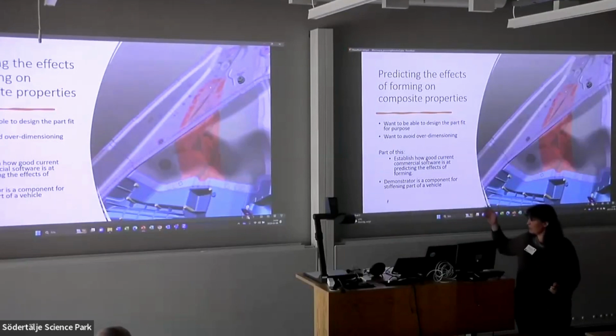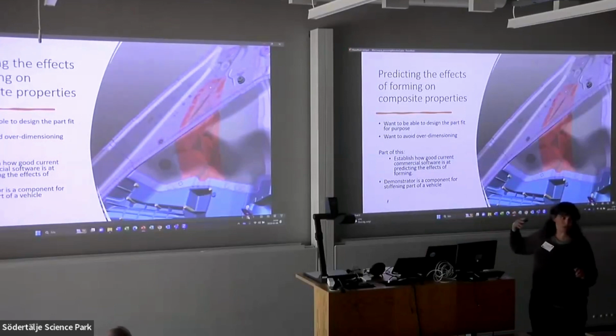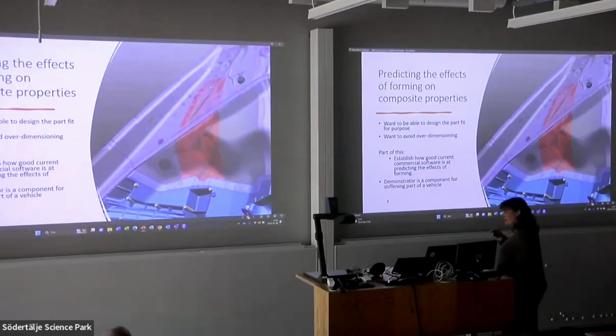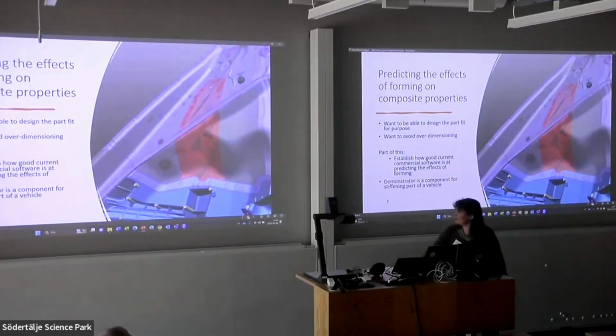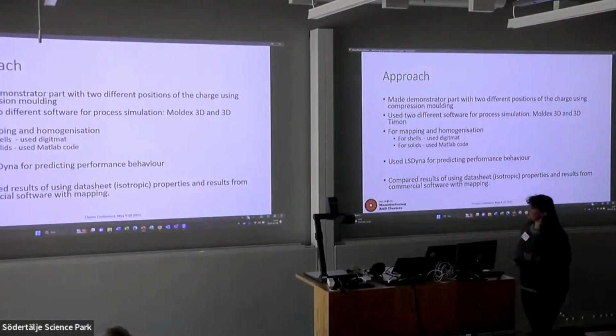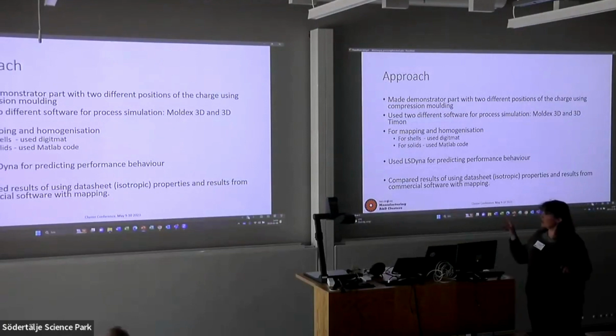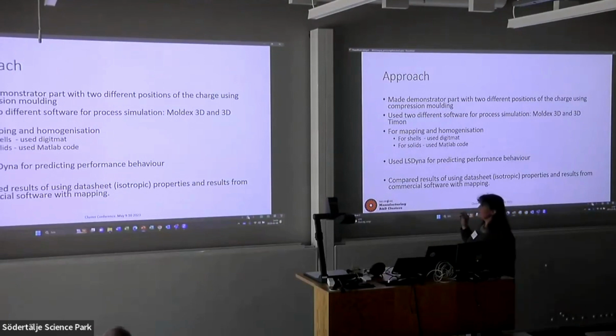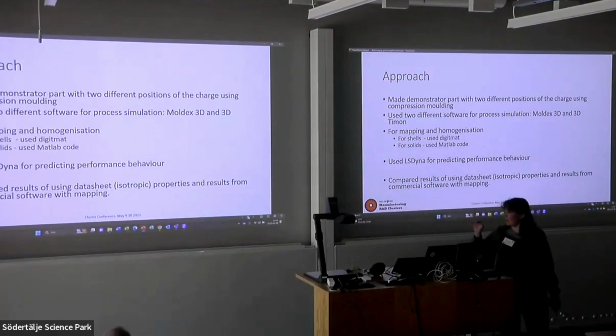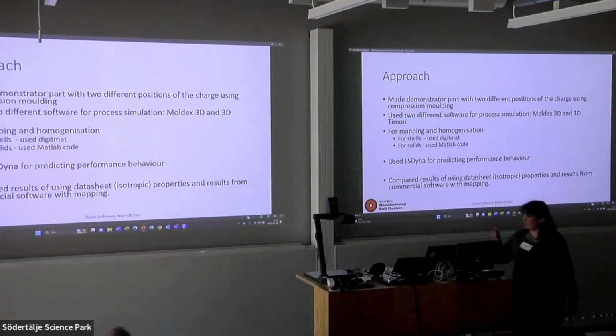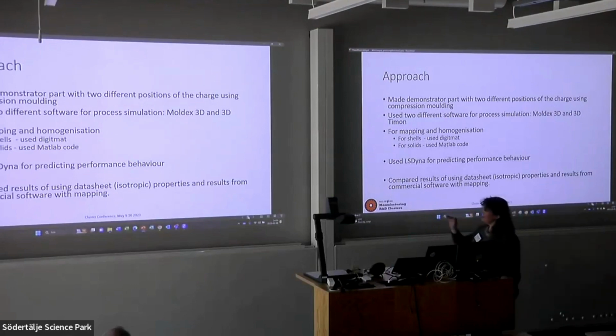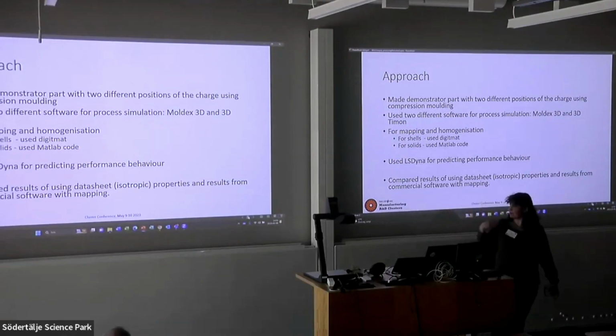This is a stiffening element in a vehicle. And we chose this to make it out of composites and to really test how good these models that we're developing and the models that are available on the market are. So we made a demonstrator with two different positions of the charge and used it in compression molding. We used two different software for the process simulation, Moldex 3D and 3D Timon. And then we did a mapping and homogenization step. For shells, this was done using Digimat, and for solids, this was using some MATLAB code we developed. And then we used LS-DYNA for predicting the behavior.